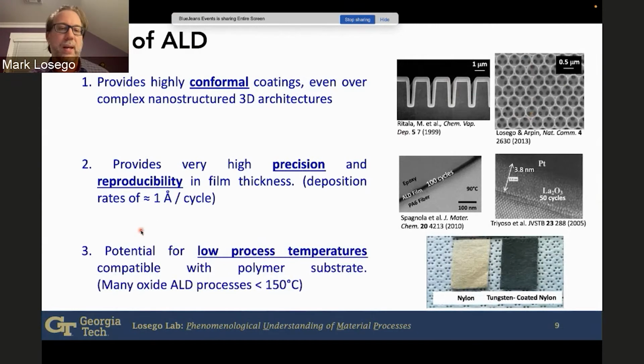And finally, it just happens that a lot of these chemistries react at fairly low temperatures, so we're able to deposit on temperature-sensitive types of materials like paper and other polymers like textiles, because we don't need to do these processes at very high temperatures, often well below 100 degrees Celsius or around 100 degrees Celsius or so.